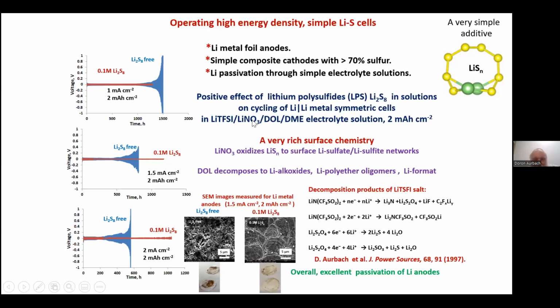When we have lithium nitrate, this is an important additive because it oxidizes sulfur, and we now have networking of lithium-sulfur-oxygen compounds on the surface, so it enhances the passivation of lithium. It appears that if we use a very simple additive, this compound, which in fact is formed through cycling, if we put this additive in from the very beginning, the electrolyte solution contains these ingredients and also the active material, lithium sulfide. So we demonstrate very nice stabilization of the lithium negative electrode.